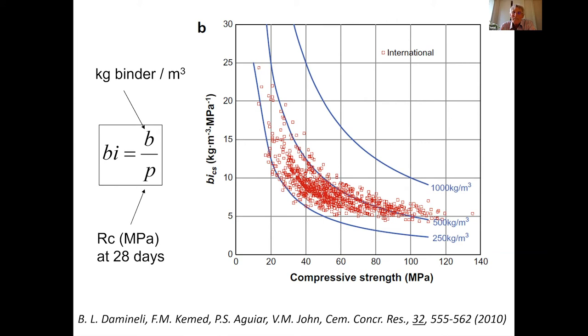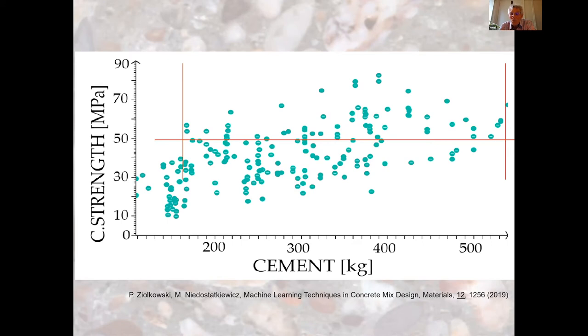Now, this is something where, as Mathieu Bauchy talked about during the conference, machine learning could be really useful. Here's a plot from another team in which people plot the compressive strength as a function of the cement content of concrete. And what you see is that in the database, I forgot how many materials, the scatter is enormous. If you look at the concrete with a strength of 50 MPa, for instance, which is pretty good concrete, some people are able to reach this performance with 100 kilograms of cement per cubic meter, or even less, while some others are using close to 500 kilograms of cement per cubic meter, which means that by optimizing the formulation, we could use much less cement than what we are using right now.